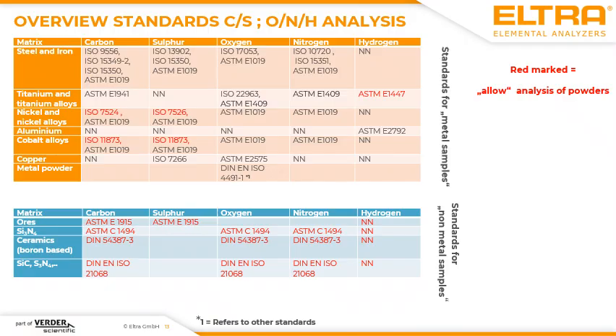First, I would like to mention the relevant standards which are published for carbon, sulfur, oxygen, nitrogen and hydrogen analysis. When you have a look at these standards which deal with the analysis of metal-based samples, for example, ASTM E1019, and all the other things which are listed here in the table, please be aware that these standards sometimes do not even mention that a sample shape of powder is in general allowed to be analyzed. And this is a general conflict when you are not familiar with this kind of analysis. So, for example, you are searching for a standard which deals with the analysis of iron-based powder. Then you have a look at the standard. But there you sometimes do not find additional information about powder-based samples.